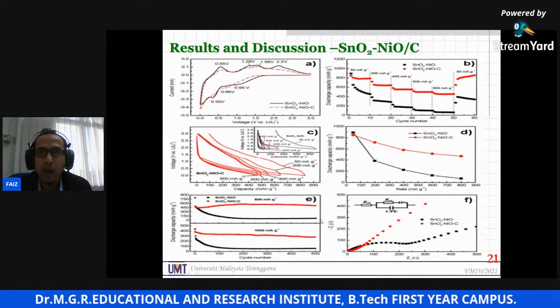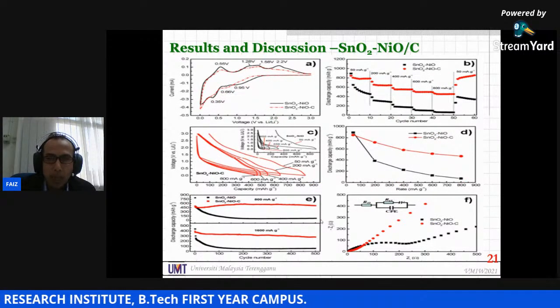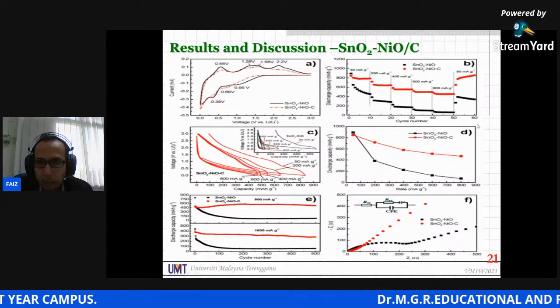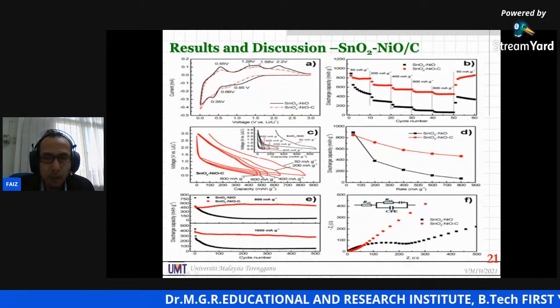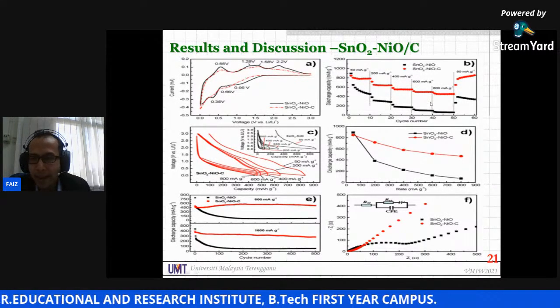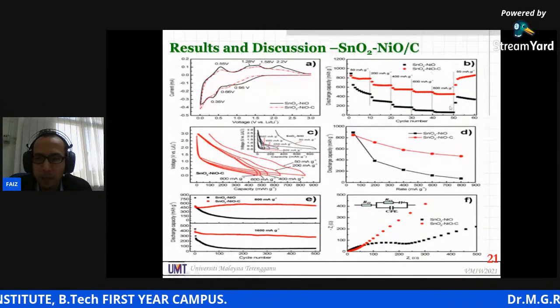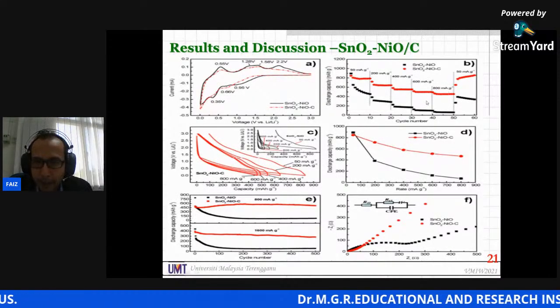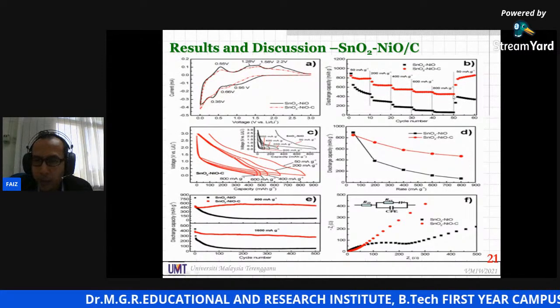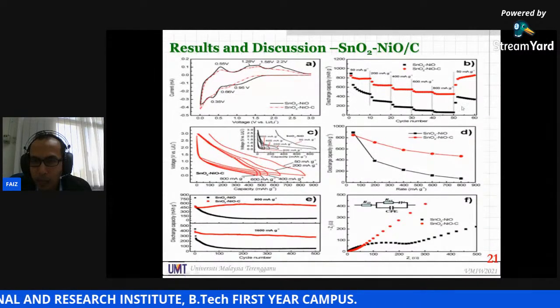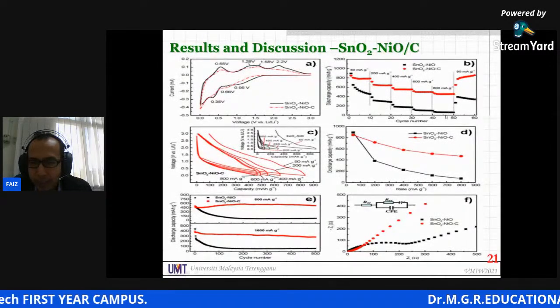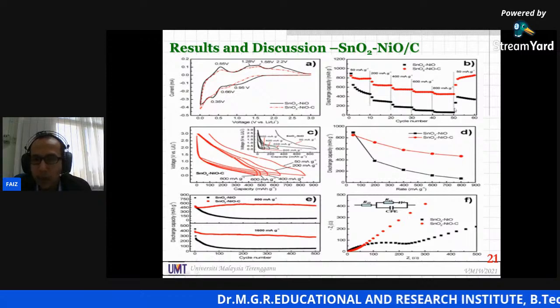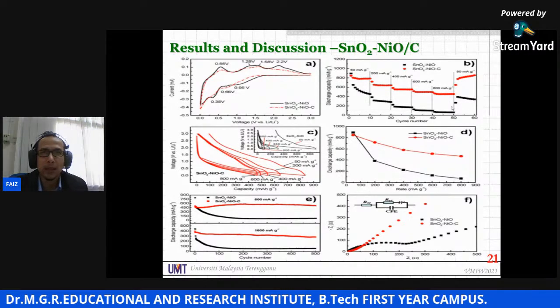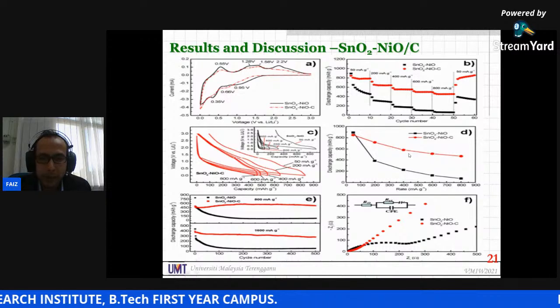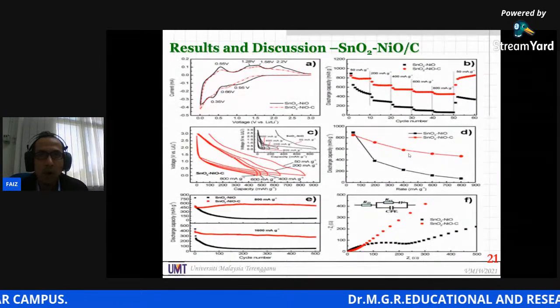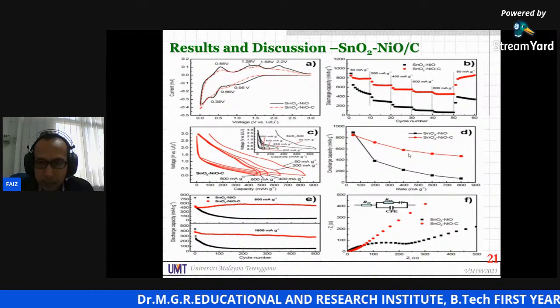Similar results were also obtained for the tin oxide and nickel oxide nanocomposites. We can see that when we test this type of material with a very high current density, as high as 800 milliampere per gram, this material can still maintain its capacity at almost 500 milliampere hour per gram, compared to the sample without carbon coating, which stands at below 100 milliampere hour per gram. So we can see that all the nanocomposite materials based on carbon coating had outstanding results in terms of capacity retention compared to the samples without carbon.